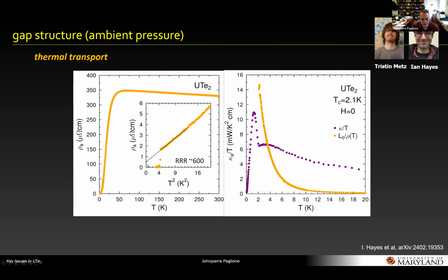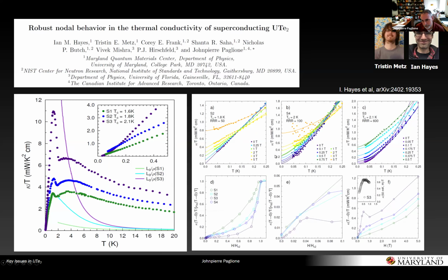It's a very low residual resistivity. So this is quite exciting because this allows us to do very careful experiments of thermal transport. You can see there's a nice signature at TC, a big rise in thermal conductivity. And so now if we look at the low temperature behavior, we can see how this evolves.